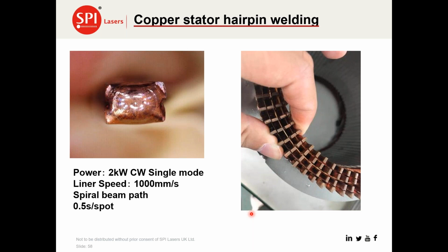We've been involved in some smaller components where the 2 kilowatt single mode using an oscillation technique is adequate, where these kind of spots are being generated in under half a second. For some applications, that's not fast enough, and people are using other laser sources at higher powers and using different technologies to control the spatter. But motors come in all shapes and sizes, and particularly for the smaller ones, we found that the oscillation welding technique can be used.